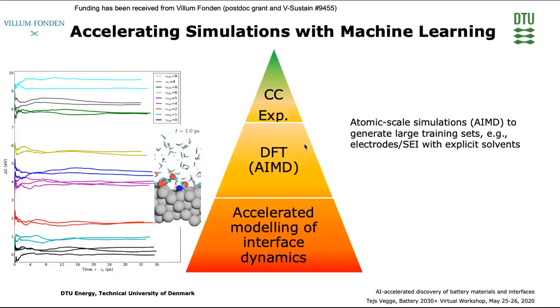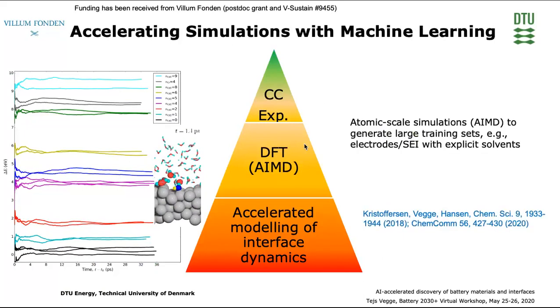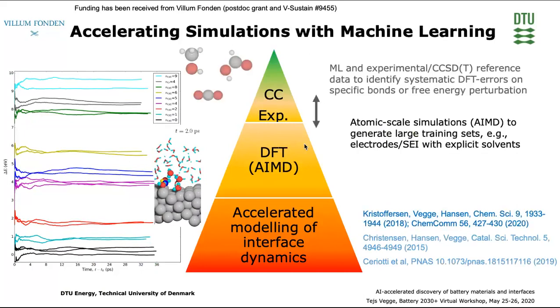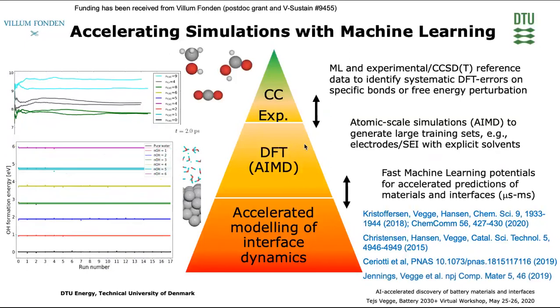Let me give you one example of one way of bridging these types of simulations. So if we start from relatively accurate density functional calculations like ab initio MD, we can run simulations of electrode-electrolyte interfaces. If we run them long enough, we also get good statistics, so we can predict properties, but still at a very short time scale. If we combine these with other machine learning-based techniques, Bayesian statistics, we can even improve upon these by identifying systematic errors using approaches developed by Rune Christensen and others, or free energy perturbation by Michele Ceriotti. We can even improve upon the DFT data and then use that data set to train much cheaper machine learning potentials that will either allow us to analyze much more complicated nanostructured materials or for studying interfaces for much longer time or length scales.